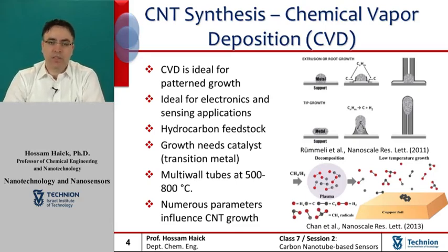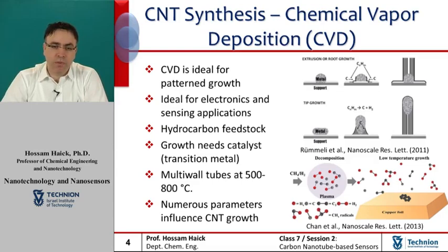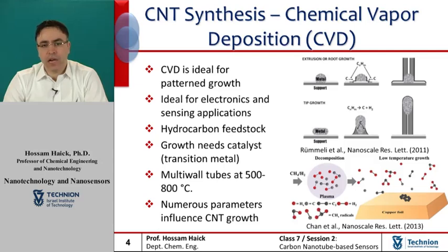As indicated in the previous slide, numerous parameters influence the carbon nanotube growth. The lower figure on this screen displays the graphene growth mechanism that involves the decomposition of the methane-hydrogen mixed plasma and the hydrocarbon radicals. The hydrocarbon radicals in the gas phase recombine with each other after they have floated for a certain distance, and the metastable carbon atoms and molecules form the sp2 structure on the copper surface, as illustrated.